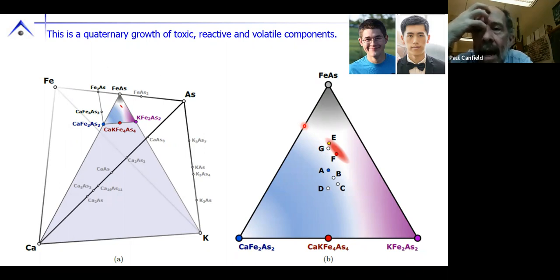This is one of the reasons why I've adopted a peeve that Ivan Schuller had for a long time, when a paper says, the triple R of 10 shows that we have high quality single crystals. Okay, well, high quality is very ill-defined, and you need to define what the quality is for the measurement you have. So for insulators, a trivial insulator, I would say it's the range of a large gap Arrhenius behavior. But on the other hand, inclusions can hide and cover a lot of sins. With Kondo materials, even dislocation lines can be a problem. We showed with ytterbium nickel boron carbon that you can anneal out dislocations, and just the Burgers relaxation vector around the dislocation line can give you distributions of Kondo temperatures that change the resistance dramatically. So quality is defined by the physics you're after.